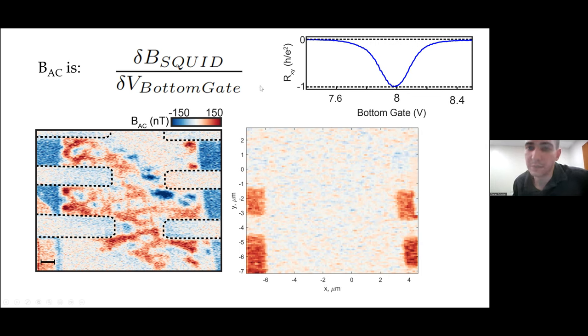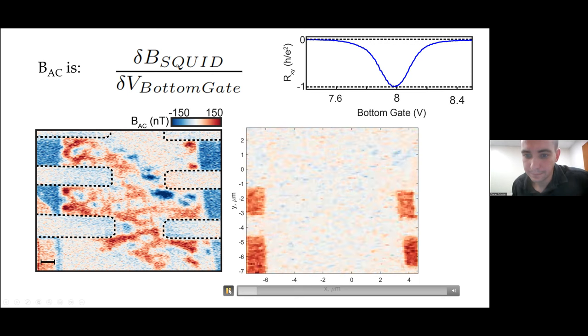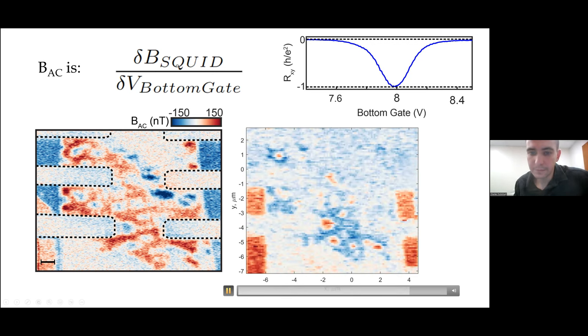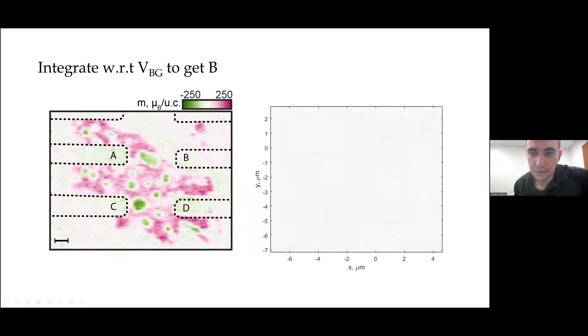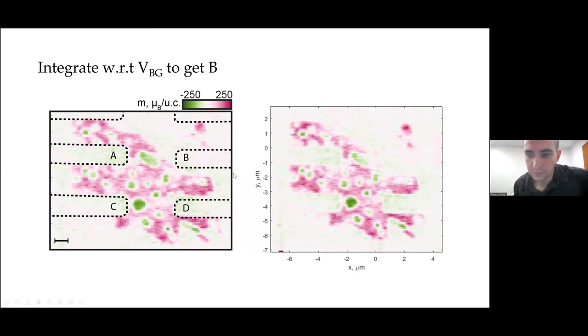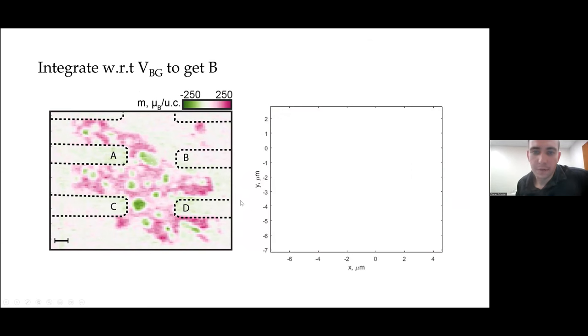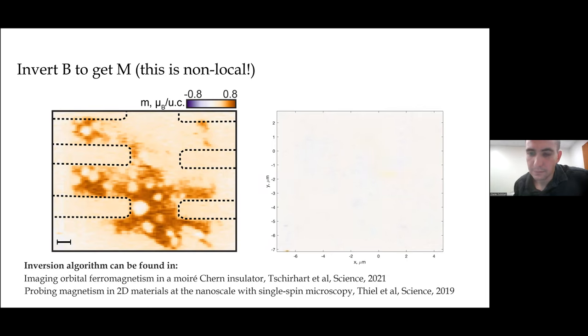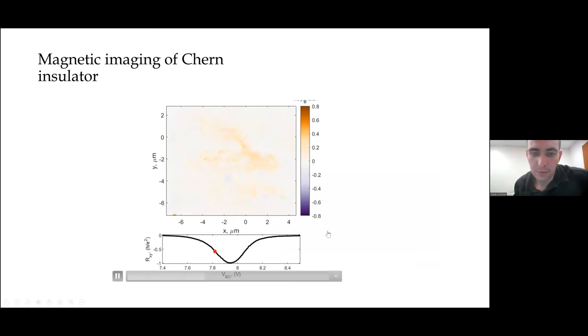So if you want to reconstruct magnetization from this data set, you need to take a video, integrate it, and then invert it to get magnetization. So I'm going to show you that video. What you're seeing is dB/dV as a function of bottom gate voltage through this quantization plateau. The next thing we can do is integrate that to get magnetic field. And finally, we can invert that to get magnetization. So I'll just show you one last time the anomalous Hall resistance and the magnetization simultaneously. You can see that as we tune through the quantum anomalous Hall peak, we can see the magnetization appear and then subsequently disappear.